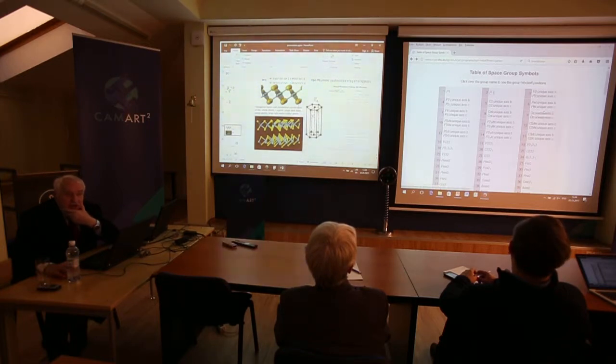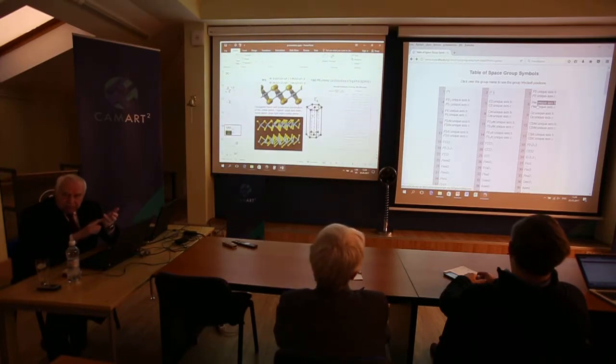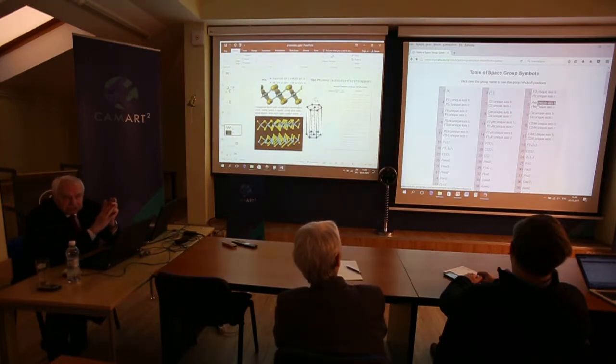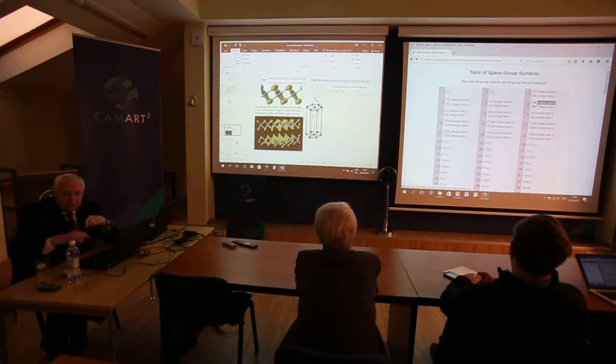Now comes monoclinic. I remind you that the monoclinic system has the following. One translation vector is orthogonal to the plane of the 2 others. The angle between the 2 others in the plane is arbitrary. So one parameter of this monoclinic lattice is this angle. And the lengths of all 3 translation vectors are different. So you have 3 parameters for lengths. In general, for the monoclinic lattice, only for the lattice, you have 4 parameters: 3 lengths and the angle.